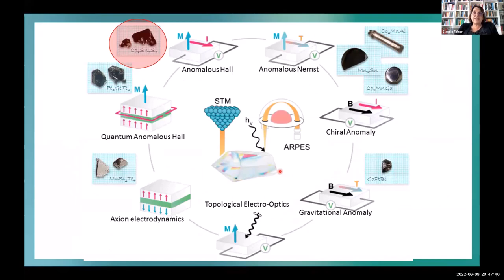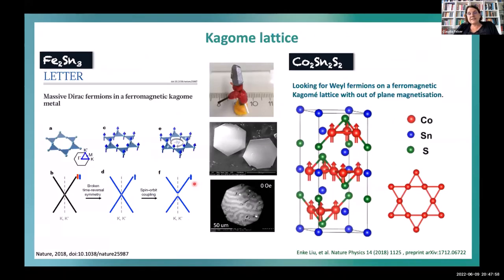Okay, so now I still have some time. I think then we thought, okay, can we find even something else in the family of Kagome? So we left the field of Heuslers and took some Kagome lattice compound, which has cobalt in it, Co3Sn2S2. And this is out-of-plane magnetized and shows an anisotropic structure, which we liked because we wanted to have spins out of plane and ferromagnetism. And we thought, okay, let's look. This is maybe a very nice compound.